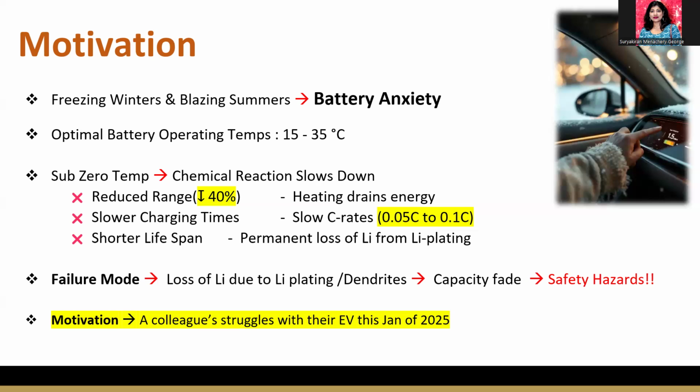Once charging finally began, the expectations of high speed charging were quickly gone, because despite being connected to a 250 kilowatt capable charger, the vehicle initially drew just 3 kilowatt, barely enough to make a difference. Whereas in warmer climates like Los Angeles, where temperatures hover around 20 to 25 degrees Celsius, charging at low SOC typically pulls in 175 to 180 kilowatt right away. But in this extreme cold weather, even after preheating, the battery wasn't warm enough to accept high charge rates.